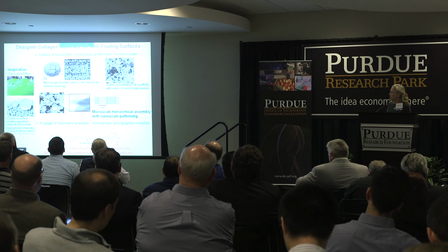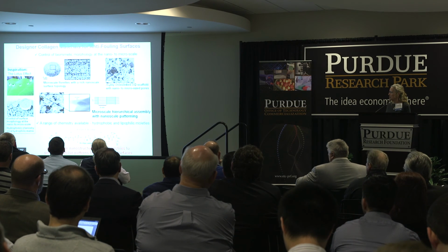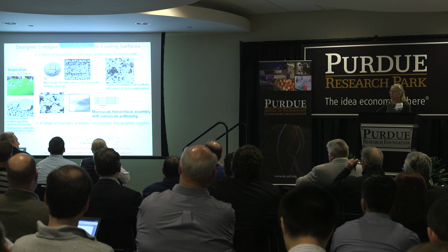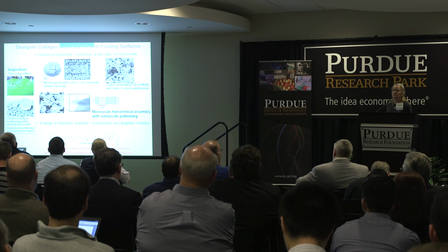And since I know every 10 nanometers what chemical functionality is right there within the materials, we can modify them with a range of different hydrophobic or lipophilic groups that can allow us to get into anti-fouling types of surfaces that could be used for implantable devices, for instance.